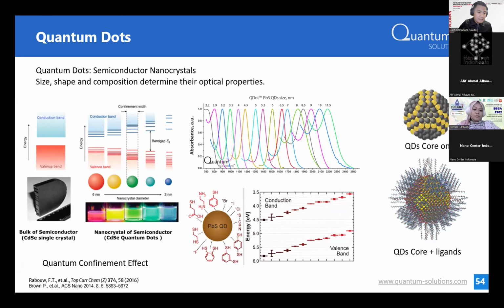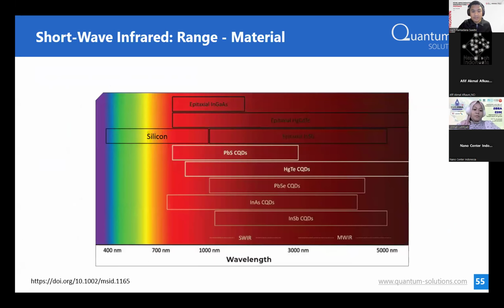So for example, in the example I have here, you have a cadmium selenide single crystal, but if you make it as a quantum dot, you can change the band gap even more, giving you a wider range of band gap. You can imagine, so the SWIR range of materials is expanded.